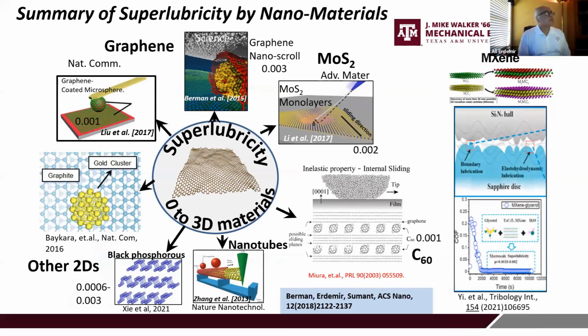There have been so many other studies that attest to the importance of structural superlubricity in one form or another. Graphene has been studied quite extensively, and other colleagues have looked at MoS2 and other 2D materials. It was also found that even in nanotubes, a similar effect could be achieved by twisting the inner and outer shells of the tube, bringing them to incommensurate states of contact.